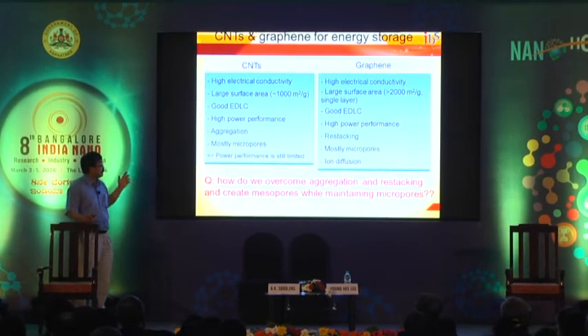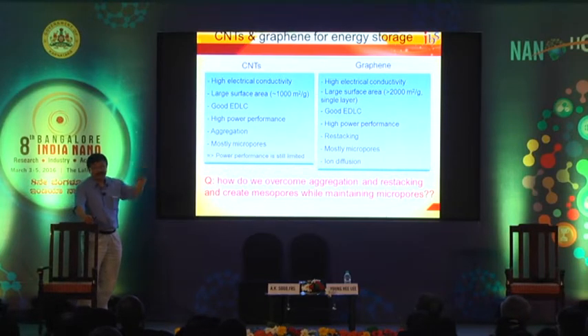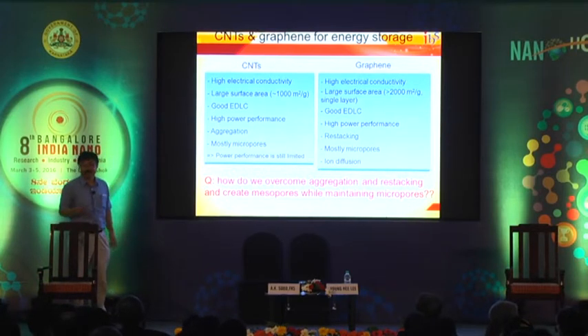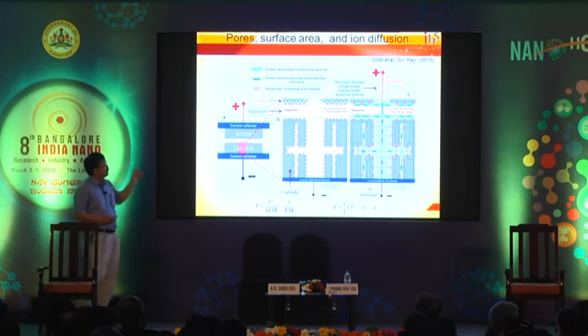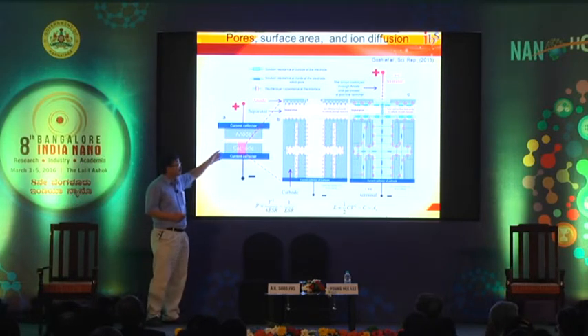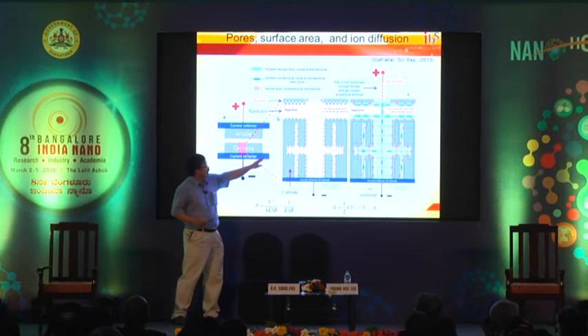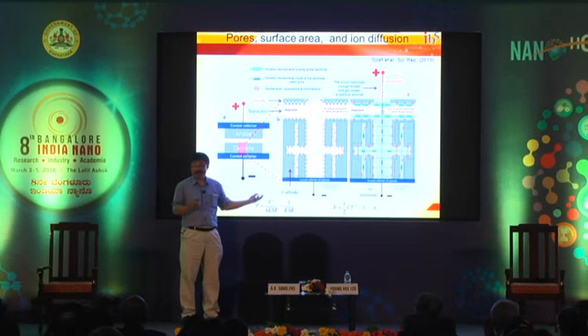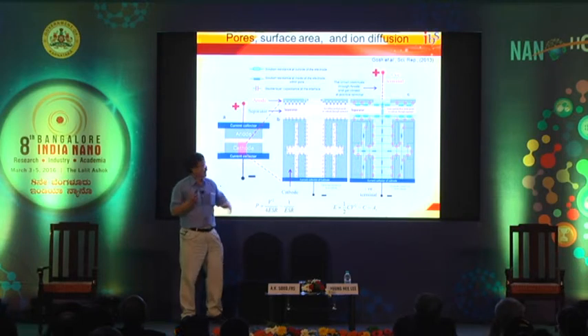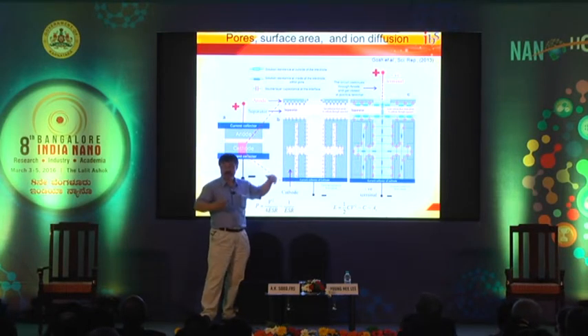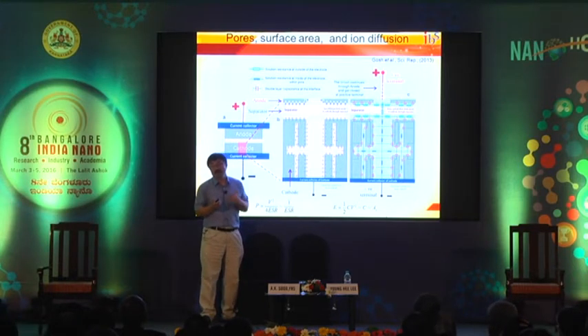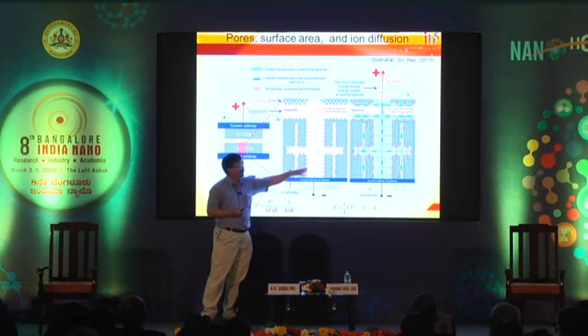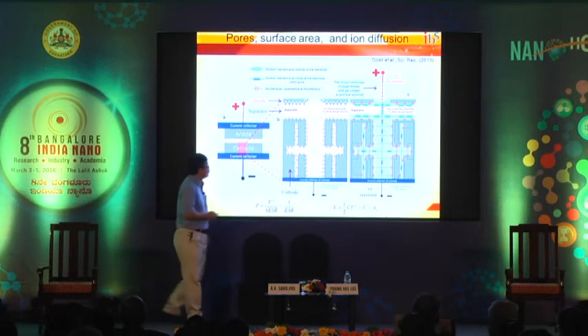So the question is, when we talk about all these nanotubes and graphene powder, and we make this film again, they all aggregate and then they kill everything. So ions cannot be diffused at all. But when you look at this electrode structure, this electrode has to have some kind of porosity to allow ion diffusion, and also has to have some micropores to store. So you have to have both, a multiporous structure. Now, how to optimize the ratio between these two is the key.